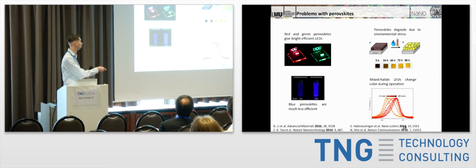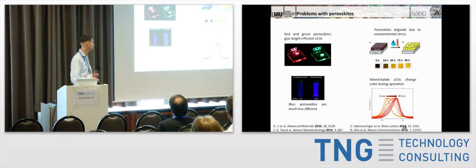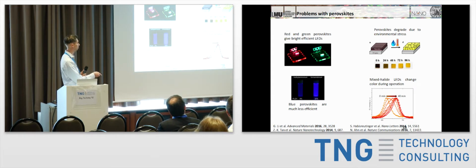So in this case, where you have bromide and iodide, they form then regions that are bromide-rich, regions that are iodide-rich, and as you know from semiconductor physics, then the electrons and holes always want to go to the energetic minimum, and so they're going to go towards the iodide-rich regions, and so essentially what's going to happen is the color of your LED changes as you're running it, which is obviously not ideal.